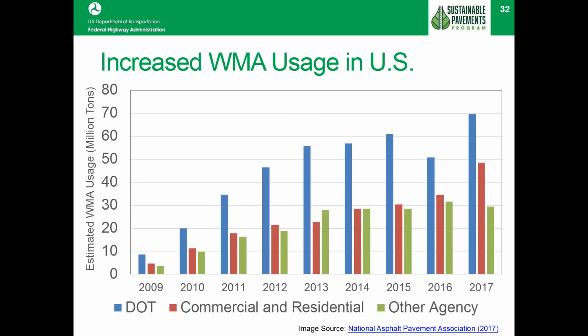This is a figure here, also provided by the National Asphalt Pavement Association, that shows the estimated warm mix usage. And this is also almost the last decade. We've seen steady increased use of warm mix additives. Again, the key immediate benefit of producing warm mix is a reduction in energy consumption required by burning fuels to heat traditional hot mix asphalt to temperatures in excess of 300 degrees Fahrenheit at the production plant. So, as you see in terms of the state DOTs, a steep increase in its use, that's the blue trend, kind of topped off about 5 years ago. But another thing that's important to notice here is there's also an increase of warm mix being used in commercial and residential construction as well as by our local agencies. That's the green trend that you're looking at there.